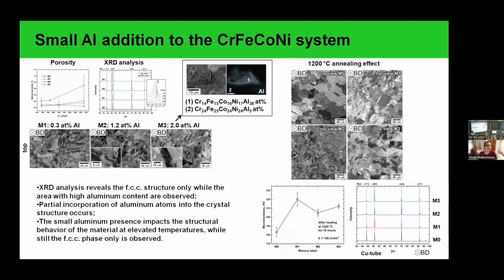The B2 phase, yes, you have commented about. It's enriched with aluminum and nickel, and we assume it is specifically this BCC phase. It generally forms for this five-component system with aluminum when the aluminum content is small, and higher aluminum content leads to the formation of the A2 BCC phases, or two of them. But on the first stages, it's the B2 BCC phase, and we see its enrichment with aluminum and nickel.